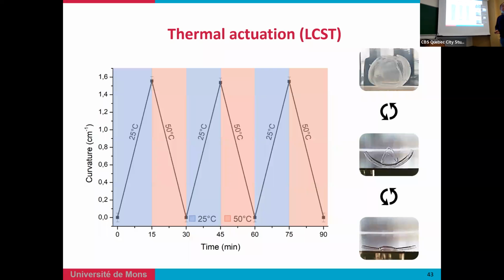In this case, we play with the temperature. We use a low temperature, where the hydrogel swells very well. Then we put the gel in hot water such that we pass the LCST and get precipitation, the deswelling of the hydrogel. You can see that this is reversible again and again over 4 or 5 cycles, showing the possibility to get this actuation.